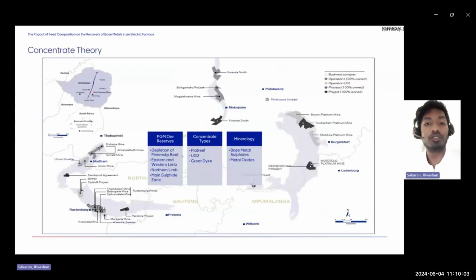Due to the depletion of the Merensky Reef that we've seen, there has been an expansion into the eastern and western limbs, into the UG2 reefs, and into the Platreef and the Great Dyke. What we have noticed, though, is that there are significant mineralogical and chemical differences between these concentrate types, with Platreef having a higher base metal concentration and a lower PGM concentration, UG2 having significantly higher PGM concentration but lower base metal concentration, and the Great Dyke being very similar to Platreef with a very high base metal concentration.